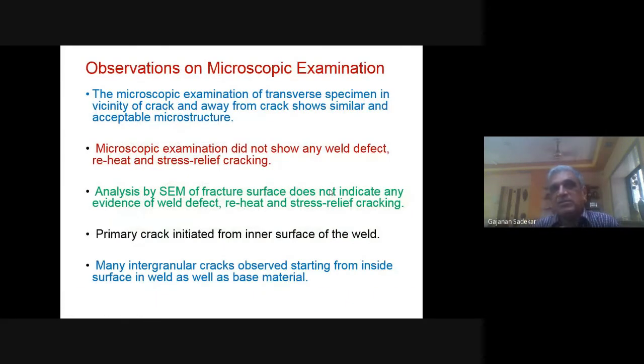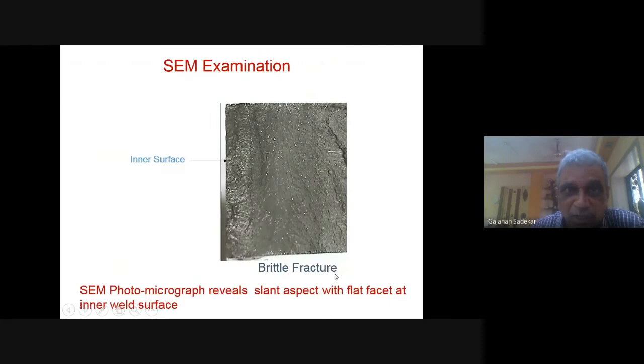So if I summarize whatever we have done in the microscopic examination: the microscopic examination of a transverse specimen in the vicinity of the crack and away from the crack showed similar and acceptable microstructure. Microscopic examination did not show any weld defect, reheat or stress relief cracking. One can say, because I am a manufacturer, that manufacturing was nothing wrong. That's possible. But some observations, for example, analysis by SEM of the fracture surface does not indicate any evidence of weld defect. The primary crack initiated from the inner surface and many intergranular cracks were observed. That's what it is. Then we did an examination with a scanning electron microscope.